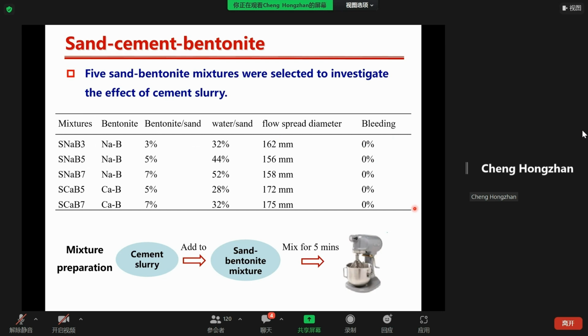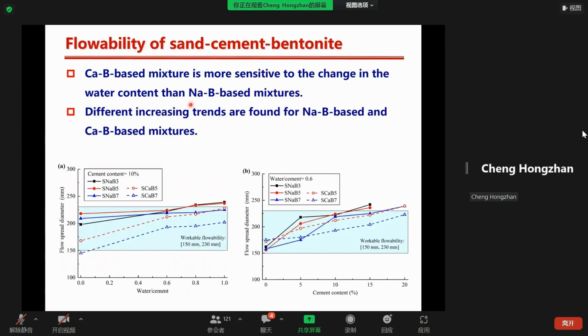To prepare the sand cement bentonite mixture, the cement slurry was added to the fresh sand bentonite mixture and mixed for 5 minutes. This process corresponds to the second phase of the cutoff wall construction, and this fresh mixture was immediately subjected to the flowability and bleeding test. From the flowability test results, both the effect of water to cement ratio and the cement content, these 2 factors were considered in our studies.